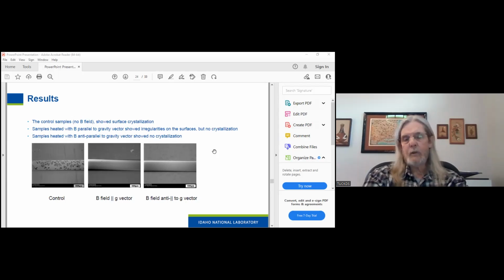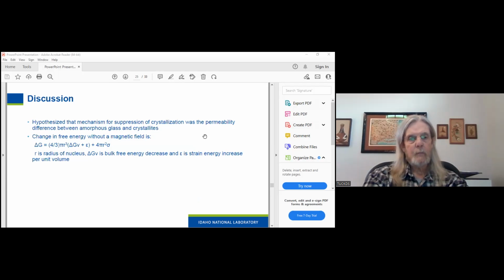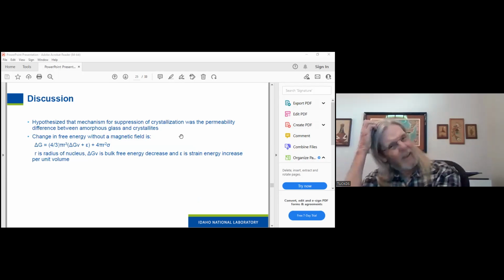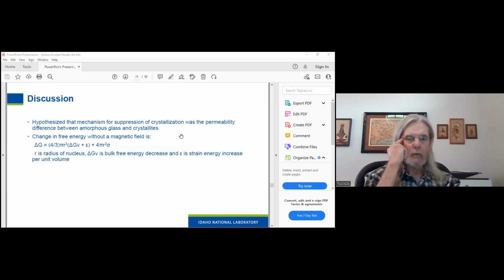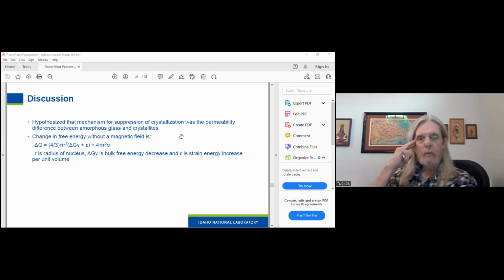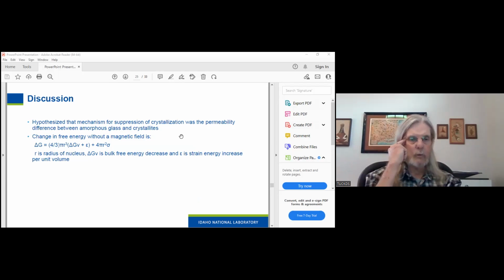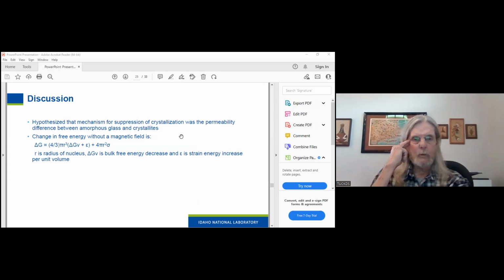So we basically got the same results on the ground as we did in microgravity. And I hypothesized that the mechanism for the suppression of crystallization was due to the permeability difference between the amorphous glass and the crystallites. And you can write the equation here for the change in free energy without a magnetic field.